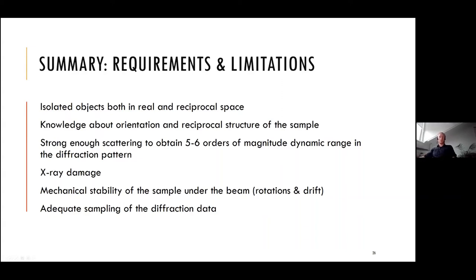X-ray damage, obviously, your sample should survive the beam. Your particles should also be mechanically stable under the beam. When you put a high flux beam onto your sample, like a nanoparticle, it can rotate under the beam pressure or other effects, and then you lose your diffraction pattern out of your field of view, and you have to search for it again. So this is quite a bit of a limitation of the technique sometimes. And you also have to ensure that sampling is adequate.